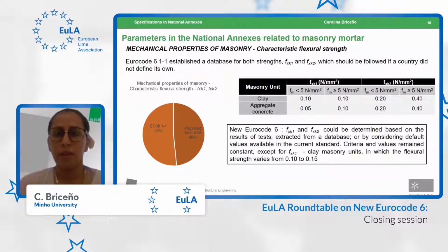Another property that is of interest is the characteristic flexural strength. According to the 1995 version, this characteristic flexural strength could be determined based on tests or based on the values given in the table. It covers two different types of failure mechanisms. The first one, which is this one, corresponds to the out-of-plane bending parallel to the bed joints, and the second one, perpendicular to the bed joints. Basically, the versions of 1995 and 2018 followed the same criteria and the same values, with the only exception for the masonry unit of clay and for mortar classes over 5 megapascal, which changed from 0.10 to 0.15.